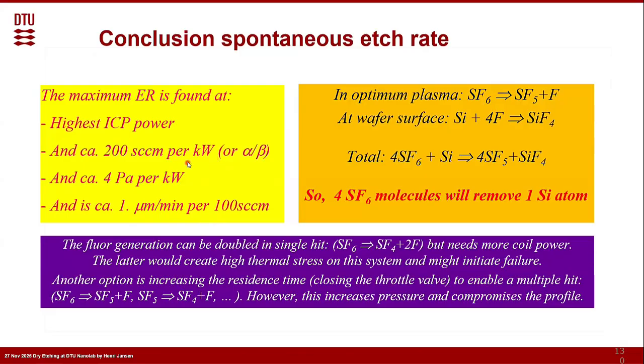That's where this happens. But as we said, we could increase the power and then it still goes up, and we create, let's say, 2 fluoradicals out of 1 SF6 molecule. But it could be that it is getting nasty hot in a reactor. Another option is that we can increase the residence time, by changing the pressure. So that's what you just did by closing the throttle valve. And we could see that the etch rate goes even further up for the same flow and power by tuning the pressure. Why is that?